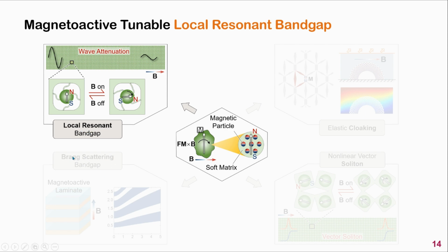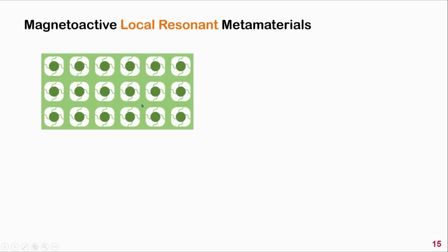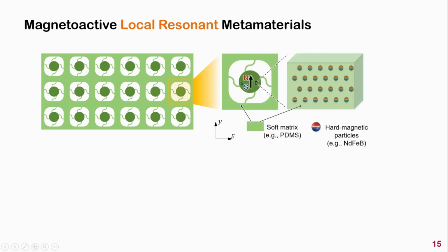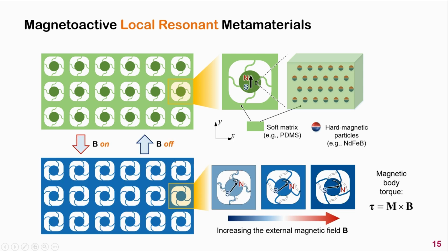Compared to the Bragg scattering band gap, whose operating frequency is determined by the lattice constant, local resonant band gap has the advantage of achieving stop wavelength with attenuation. Consider the local resonant metamaterial system shown here. The mass core of the local resonator is made of hard magnetic materials, with remnant magnetization shown by the black arrow. Consider that an external magnetic field is applied, such as in the horizontal direction. Magnetic body torques act on the particles which will rotate the mass core.